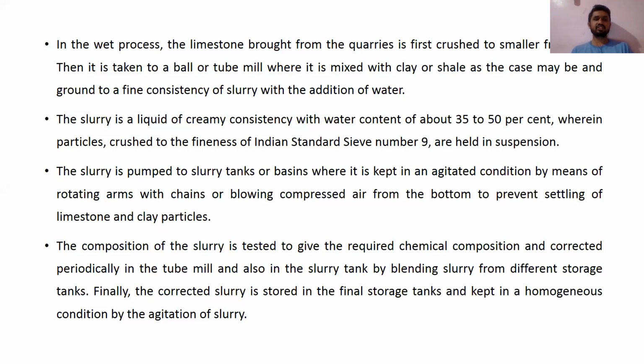Okay, the composition of the slurry is tested to give the required chemical composition, and corrected periodically in the tube mill and also in the slurry tank by blending slurry from different tanks. Finally, the corrected slurry is stored in the final storage tank and kept in a homogeneous condition by the agitation of the slurry. So as we have stored the slurry in the slurry tank, some amount of slurry will be taken from that tank and we will test it for the corrected composition, all the chemical composition.